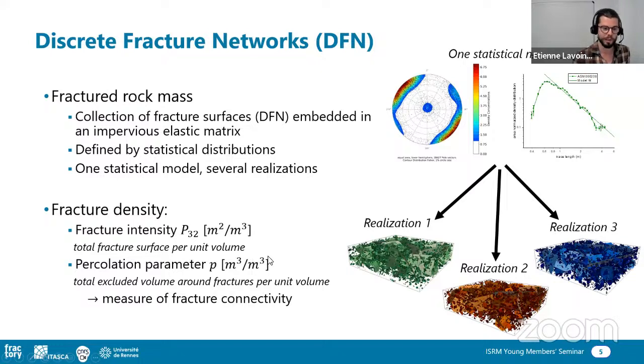But you can also define fracture density using the percolation parameter, which is defined mathematically as the total excluded volume around the fractures per unit volume. So it is unitless, and it has been widely used in hydrogeology to characterize the connectivity of fracture networks, because if this quantity is larger than a certain quantity that we call the percolation threshold, the network is statistically connected. So depending on what you are doing, it may be relevant to characterize density by both quantities.